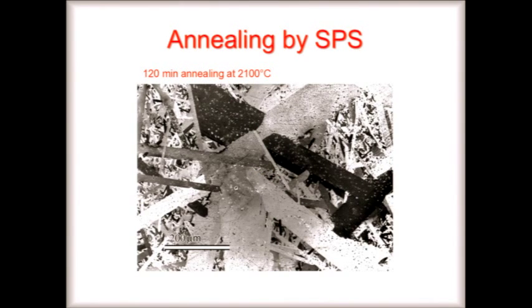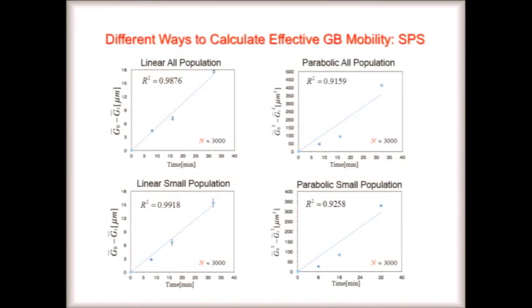This is 200 microns, more or less the diameter of our hair. These are massive silicon carbide crystals, after 120 minutes. Here there's a real problem in extracting mobilities because of the shape, and we started playing with the kinetic models that exist. They're really, really boring, and I won't kill you with that, but this is just a linear analysis of the entire population of grains. This is only the small grains, not the elongated large grains. We did the same thing with parabolic, and I must admit we went on and played with this matching of the kinetics.